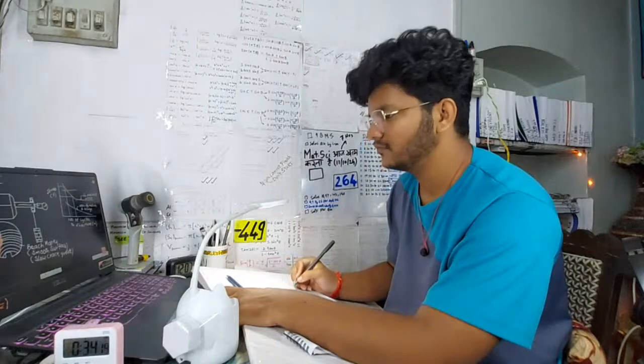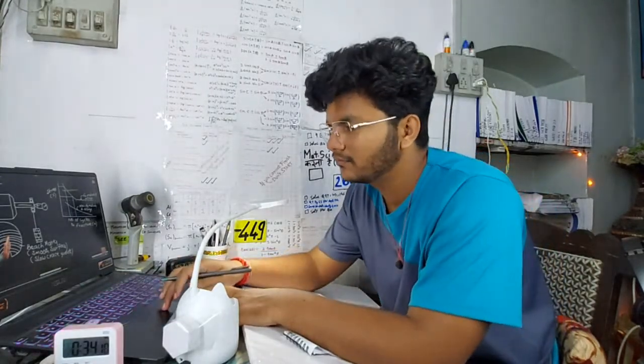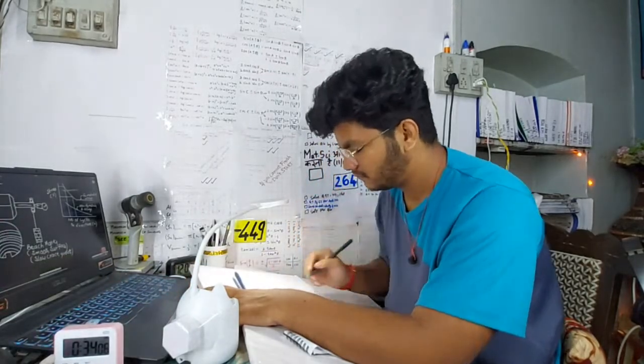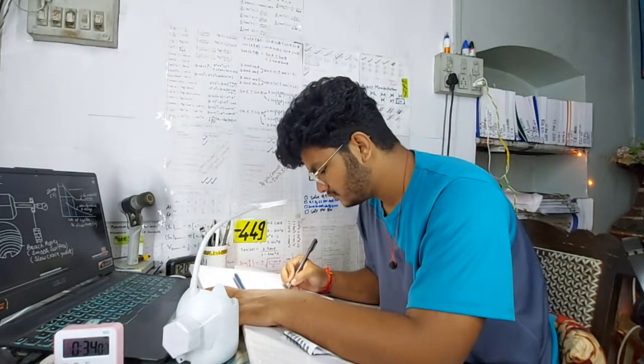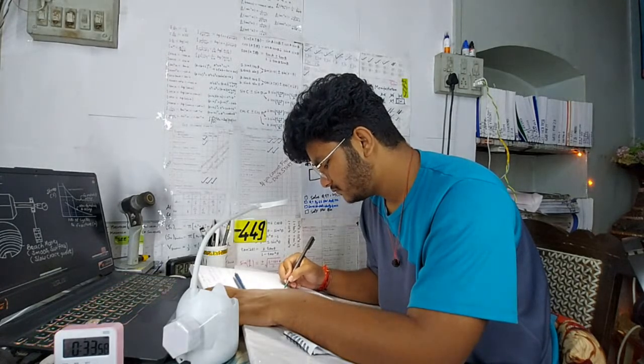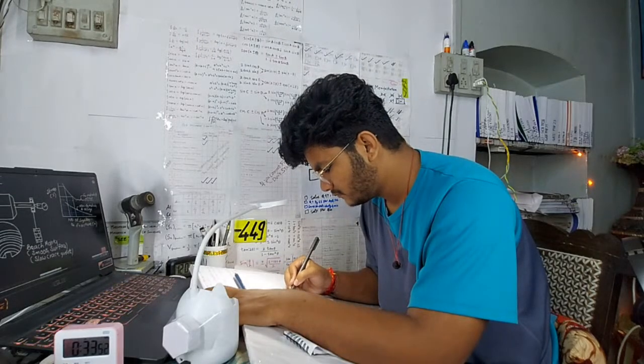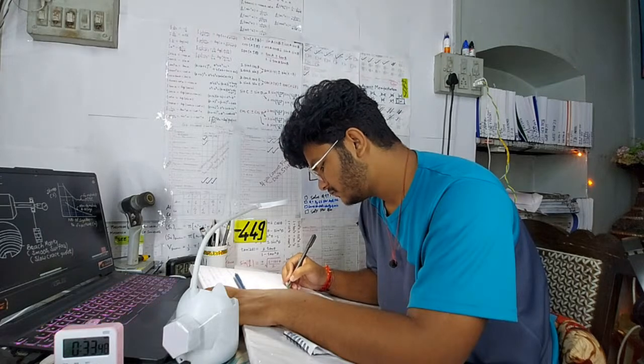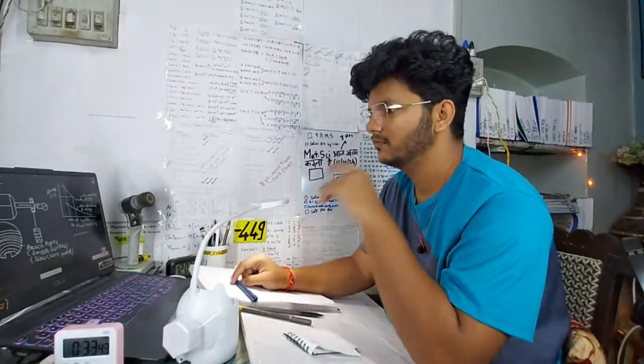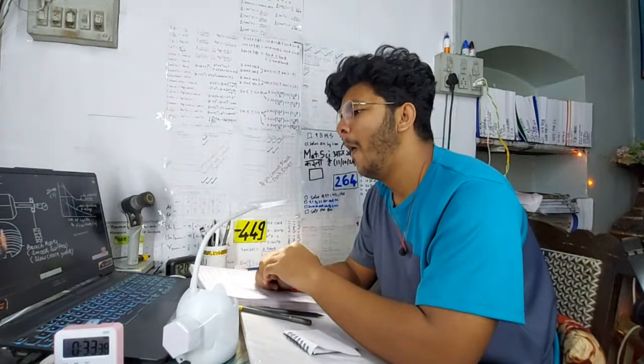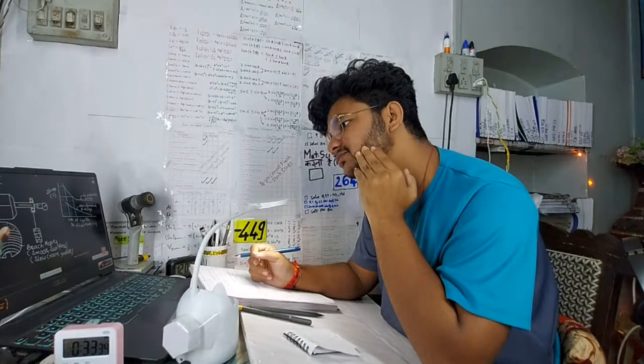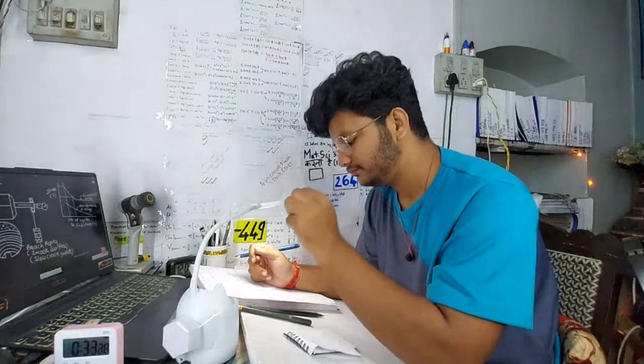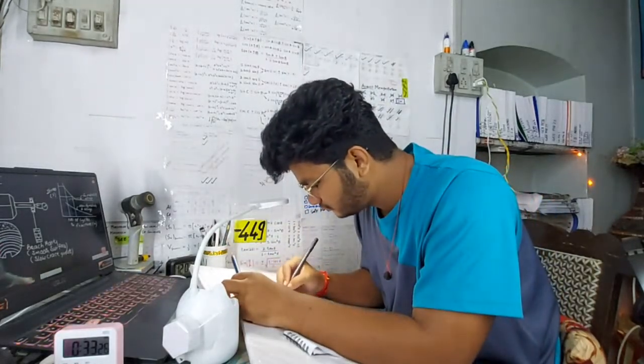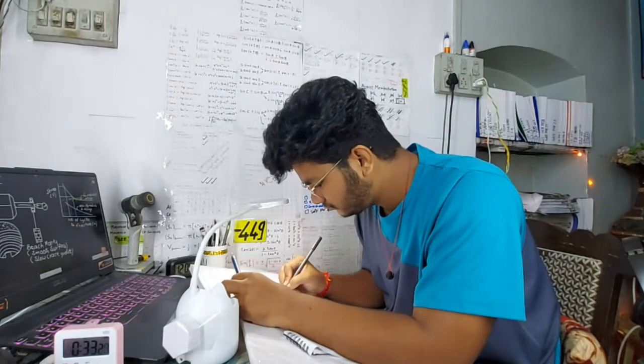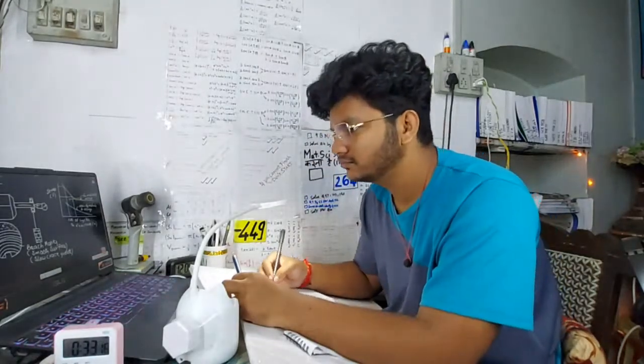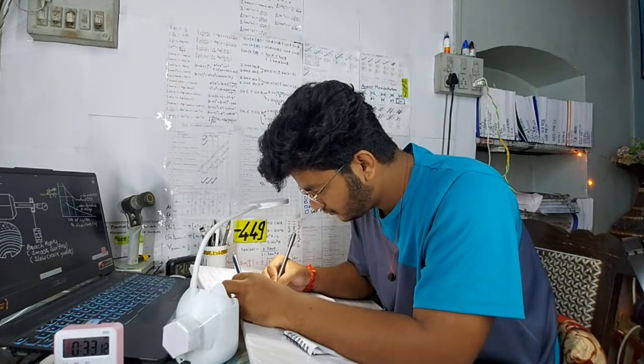Now, when the crack propagates almost 2/3 of cross section, in the last 1/3 portion of the cross section area, the crack propagates speedily. When the crack propagation takes place speedily, rough surface will be created. So we try to understand here. This rough surface, rough region, indicates fast crack growth.